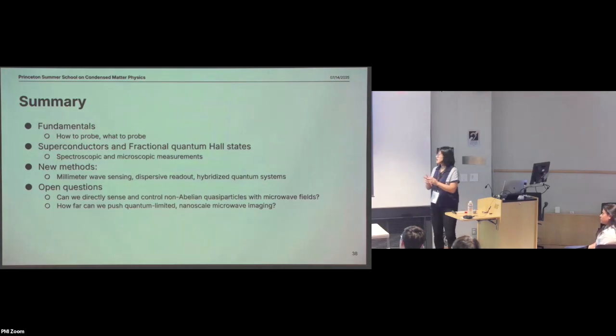Yeah, so this is the first question. For the second question, did we see superconductivity? We didn't see superconductivity. Our current measurement scheme with MIM is not super compatible with measuring superconductivity. So those new schemes can, but the old schemes cannot. The reason is we are only sensitive to a range of conductivity, but we're not that sensitive to inductance, because the tip is capacitively coupled to the sample. And that made it hard to tell the difference between a conductor and a superconductor.